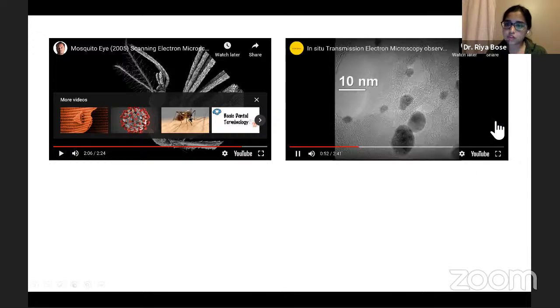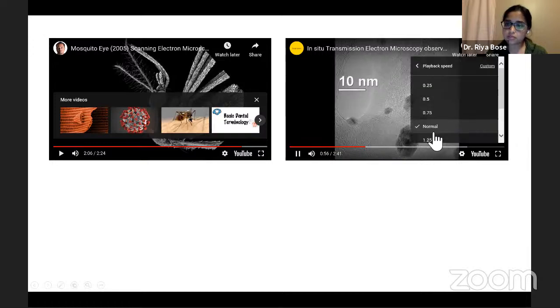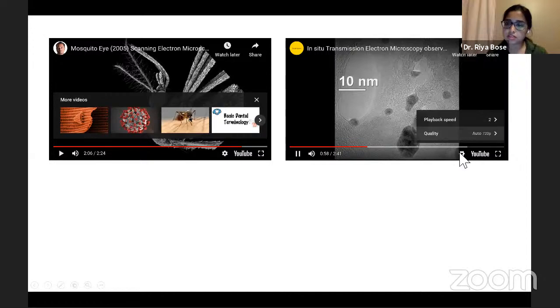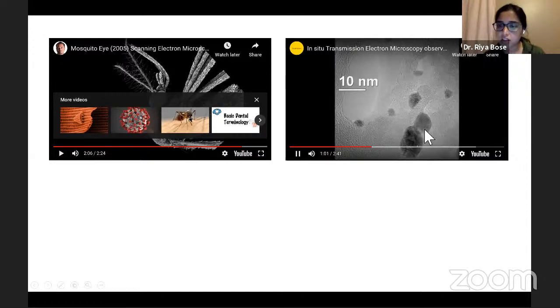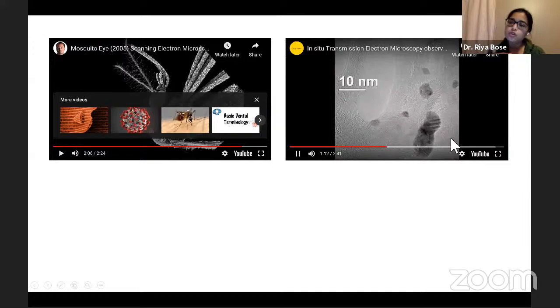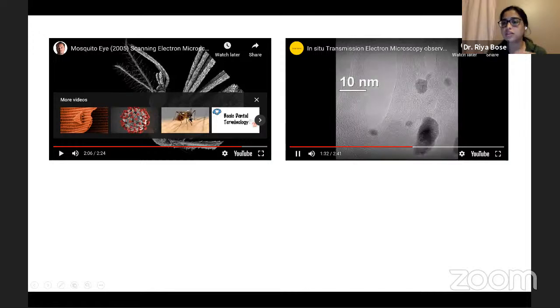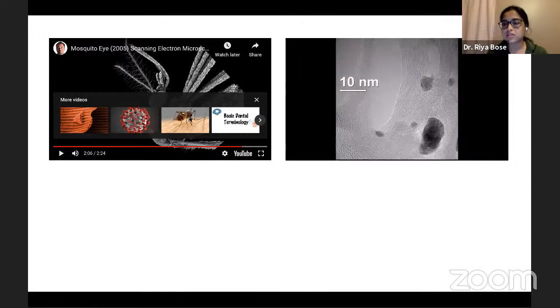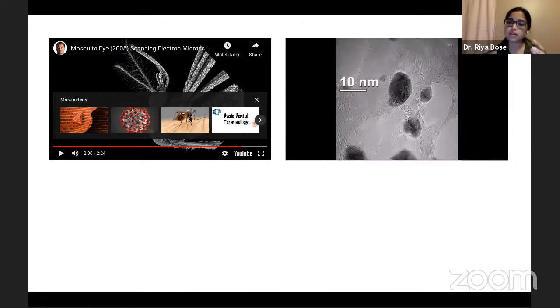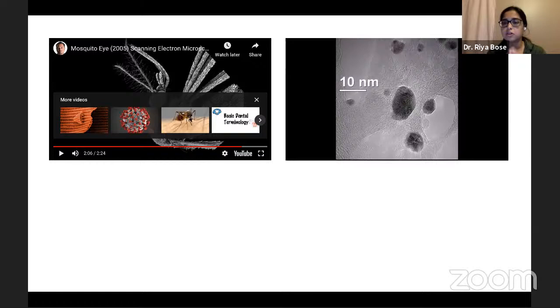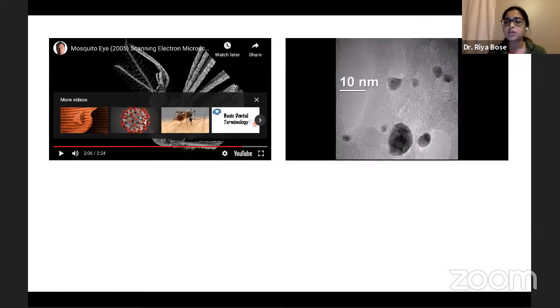So I can actually increase the playback speed a bit so it will be faster. And now you can see they have kind of diffused inside each other, and you can see how the lattice planes are changing. So these lines that you are seeing on the screen are basically lattice planes of individual atoms, and they are connecting with each other, and it is showing the rearrangement that is taking place inside the nanocrystals. And as you can see now, it is as if two particles are just together forming one bigger particle. And you can observe such fascinating phenomena in nanoscale directly under transmission electron microscopes.